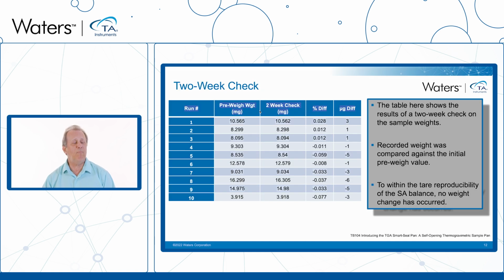Now, with these 10 pans, we did a second experiment. We left them sitting on the autosampler tray for 2 weeks. We then loaded them back into the assay, and we compared the mass at the end of 2 weeks with the mass of the sample that was recorded at the very beginning of when they were loaded. And that's what the first 2 columns show here.